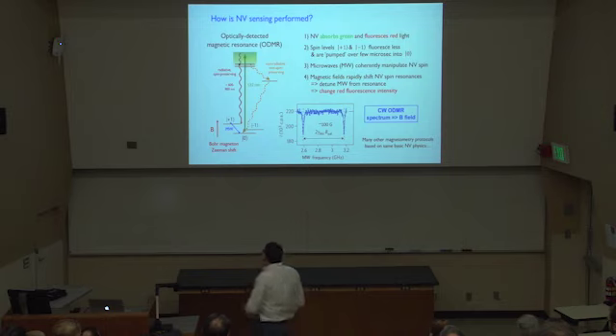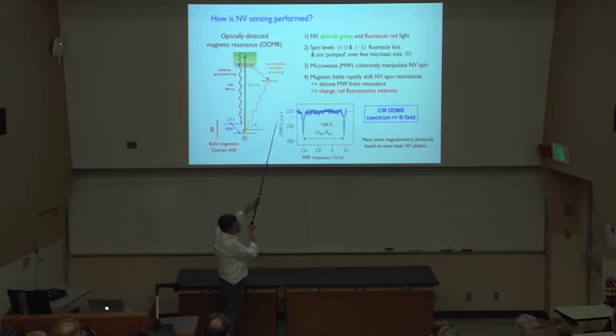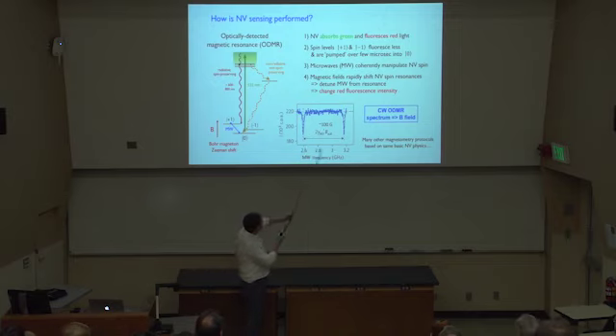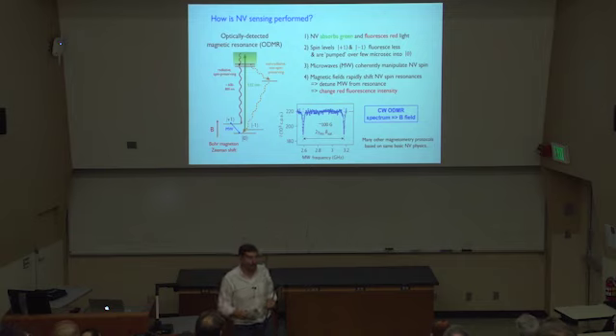All right? So this is a piece of data. For a single NV, it's the intensity, the number of photons, hundreds of thousands of photons per second, counts per second, coming from this particular NV. The optical collection efficiency is not perfect. It's not a perfect experiment in many ways. It's in a static magnetic field along the quantization axis of around 100 Gauss. We're going to keep that fixed in this experiment as an example. And what we're going to do is spectroscopy as we apply near-resonant microwaves and find out how the intensity of the red photons varies as a function of the microwave frequency.